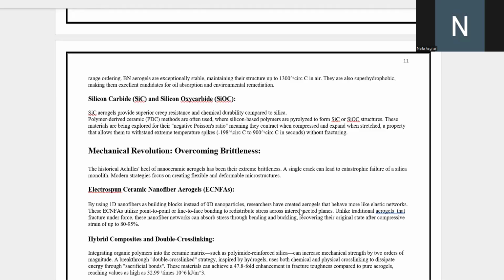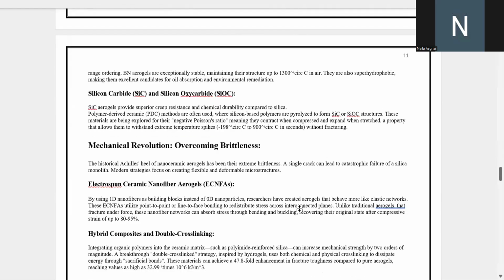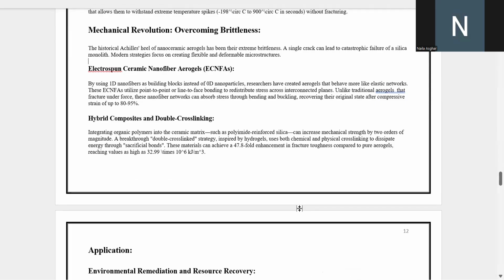And the second strategy is to create hybrid composites by infusing a ceramic skeleton with tough polymers, like embedding a flexible net within a brittle structure. The most advanced method uses a double cross-link design inspired by the toughness of biological tissue. This creates a sacrificial bond inside the material that breaks under stress and absorbs a massive amount of energy, preventing a crack from spreading. This approach can make these aerogels nearly 50 times tougher than their brittle predecessors.